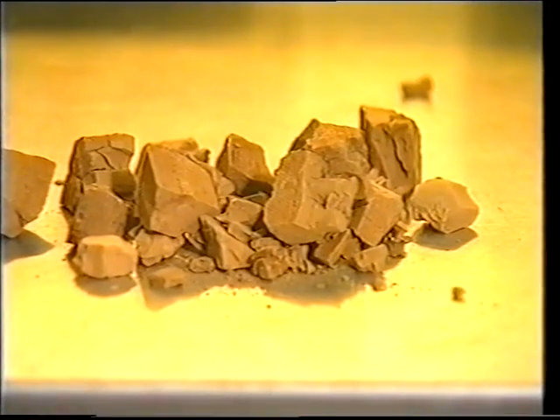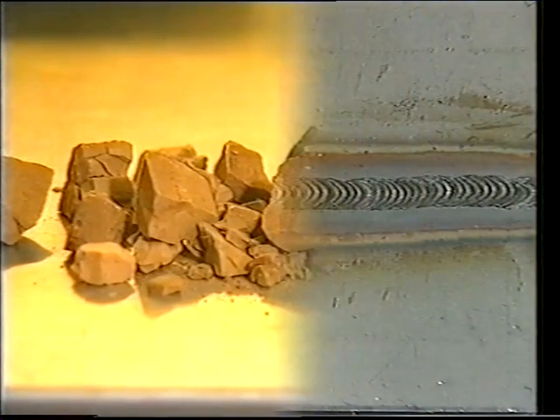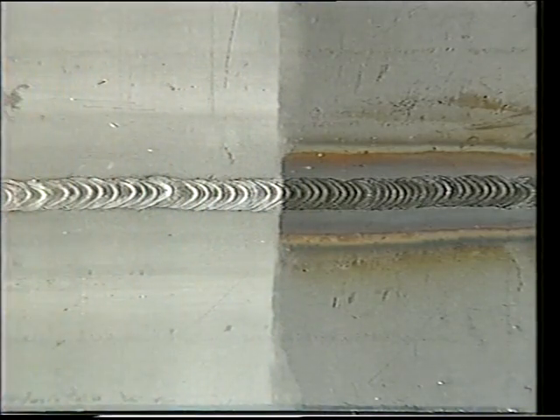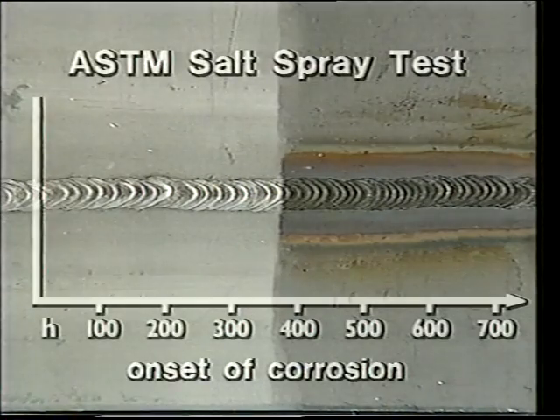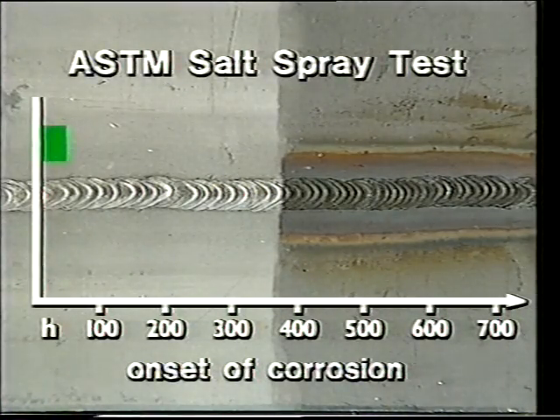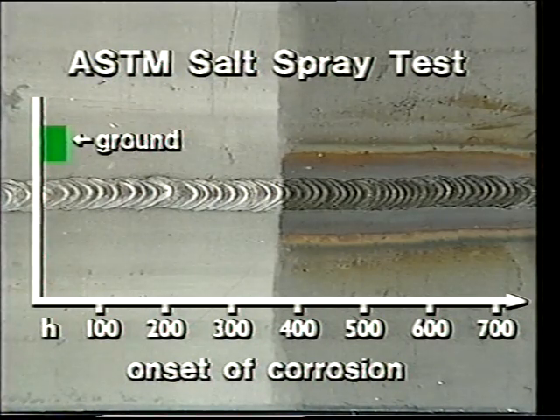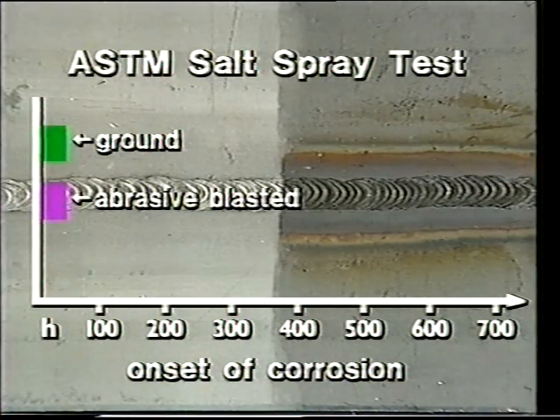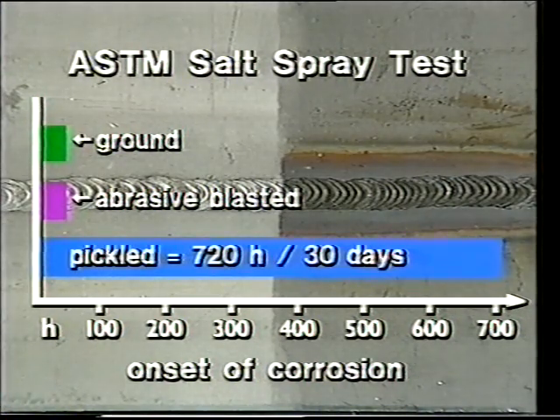Any tarnish or scale present before treatment is removed in a single step. The result is a clean surface with reactivated passive layer. In the ASTM salt spray test, ground and abrasive blasted samples exhibited corrosion effects after only 24 hours. Pickled specimens, however, remain corrosion-free for at least 720 hours. That's 30 days.